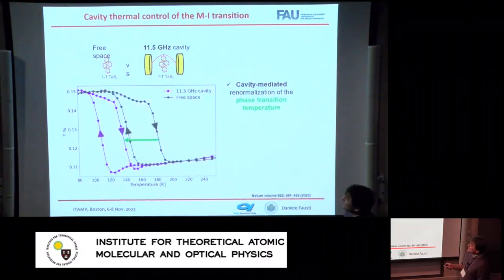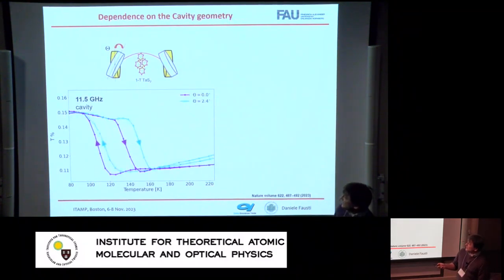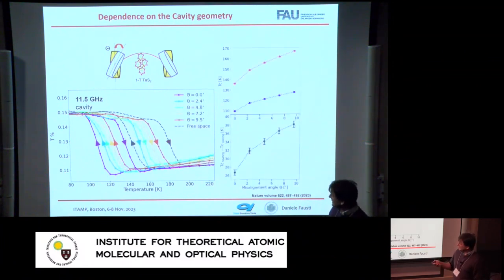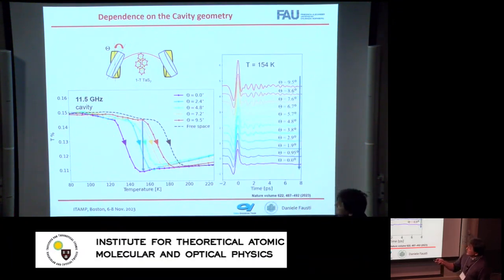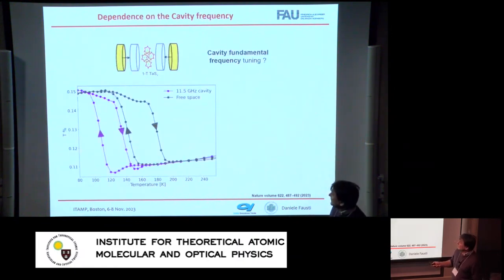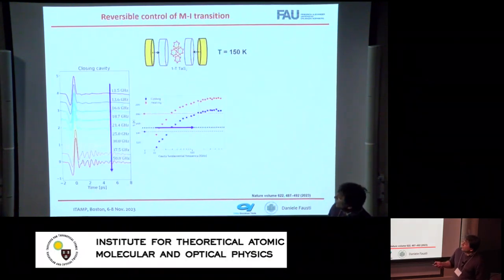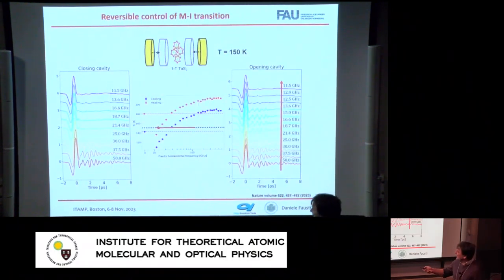And it is controlled by the mirror in the sense that if I plot the hysteresis as a function of the mirror angle, I can misalign the mirrors and go back to almost the hysteresis I have in free space. I can even fix the temperature of the support, and just by changing the mirror, I switch from metallic to insulator, and I can do the opposite in different conditions. I go very fast because the chair is getting nervous, but this is all published, so you find it in the publication. So I essentially control whether the system is metallic or insulator just by controlling the mirrors.